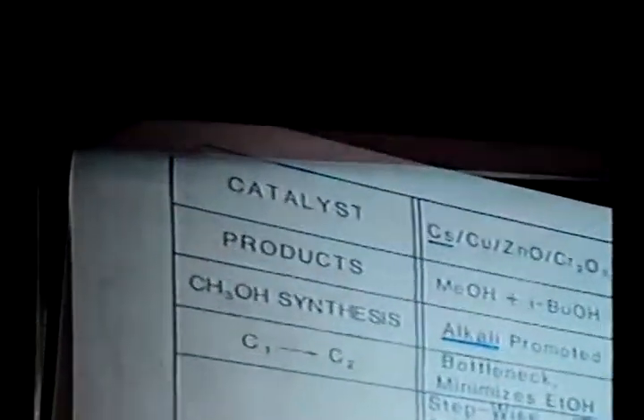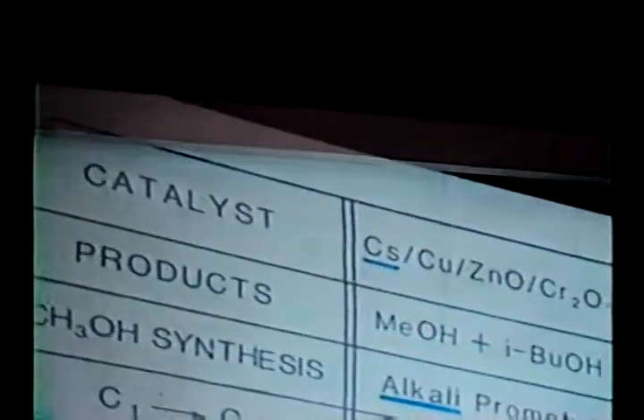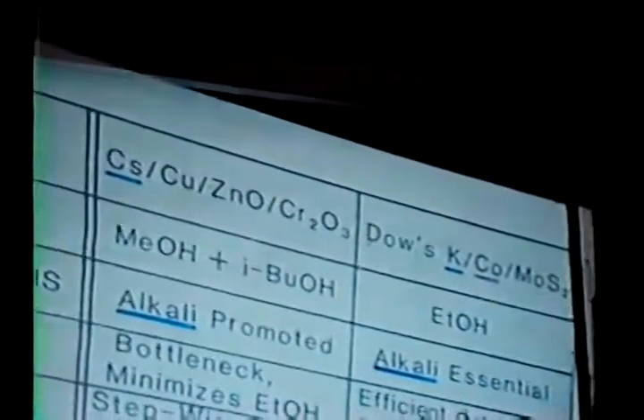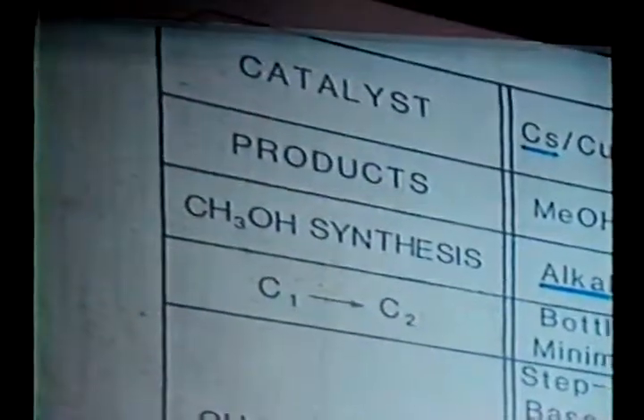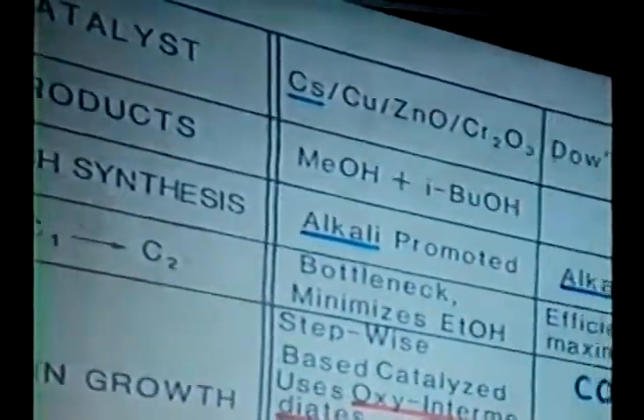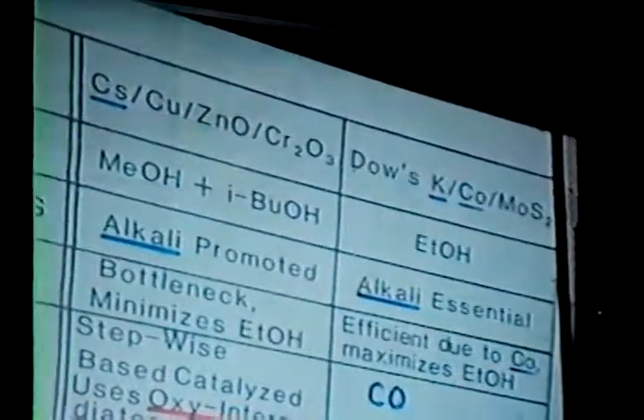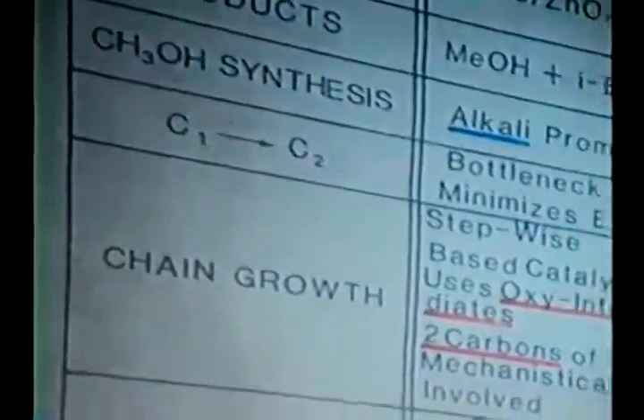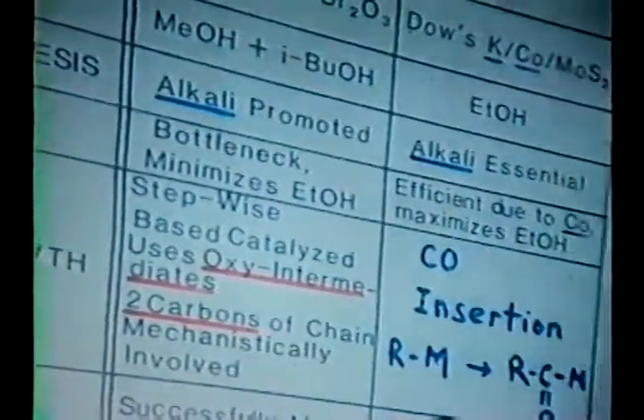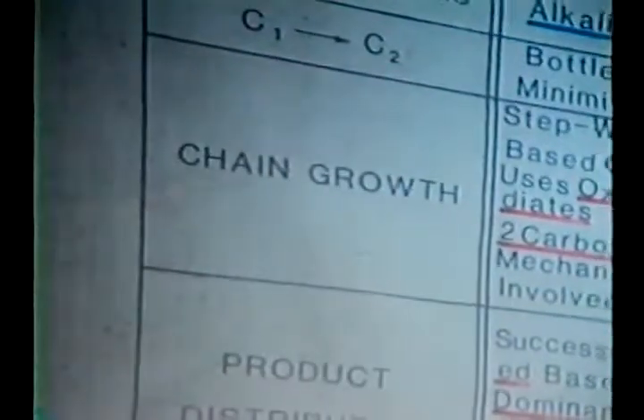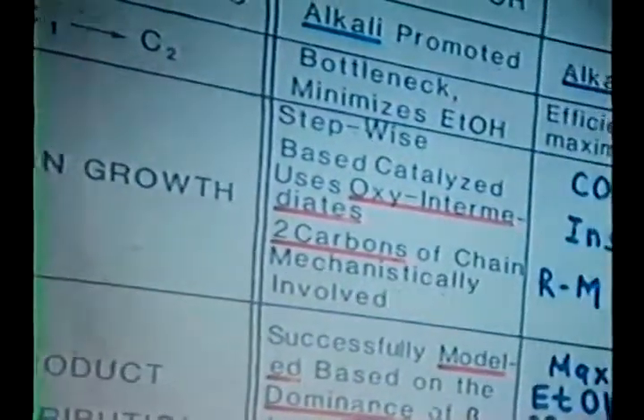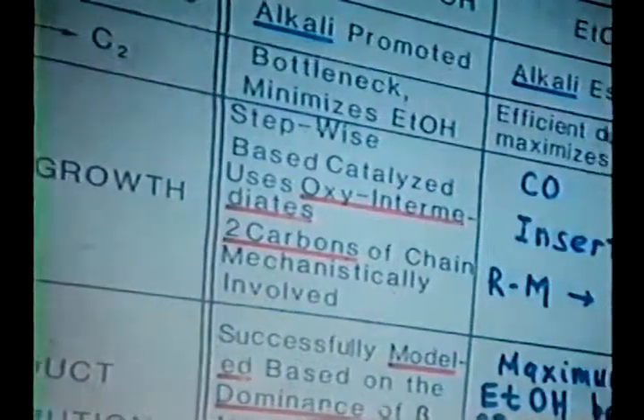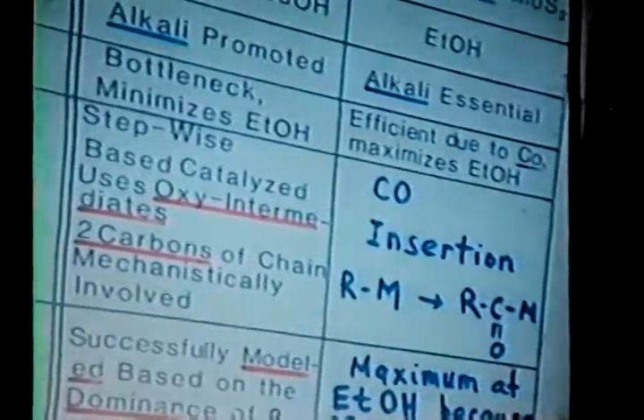Now, in my last slide, imagine what you can do with these two systems. There's no doubt that the copper zinc oxide catalyst is still the winner in methanol synthesis, the C1 synthesis. The cobalt molybdenum disulfide is the winner in C1 to C2. But what you can do is synthesize methanol on copper zinc oxide, dump that methanol either in the same reactor or in two reactors onto the cobalt molybdenum disulfide to get ethanol if you want to. If you don't want that ethanol and want a higher molecular weight product, you take that ethanol and dump it on cesium copper zinc oxide to get these higher molecular weight products. So there's a great variety between these two systems in which you can manipulate the product composition for the purpose that one might have.